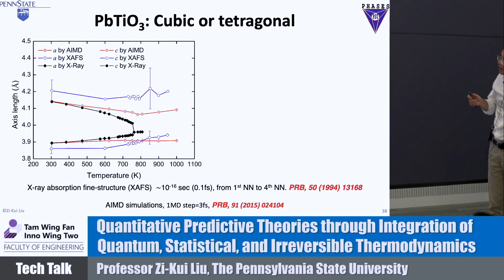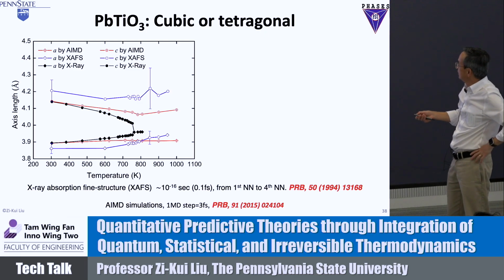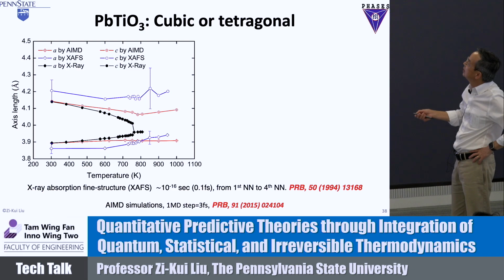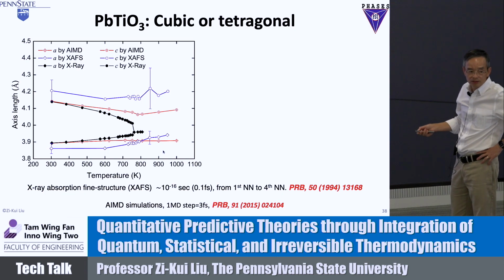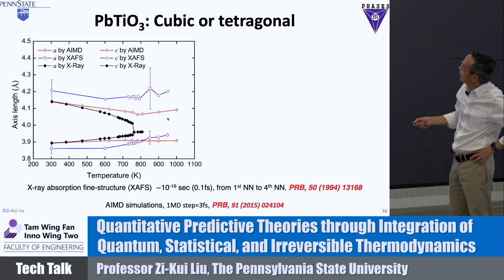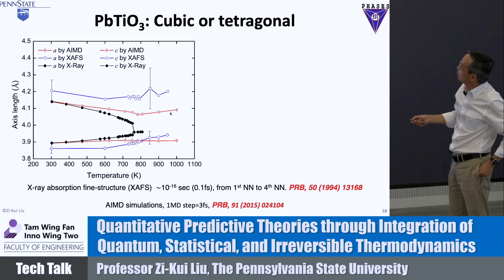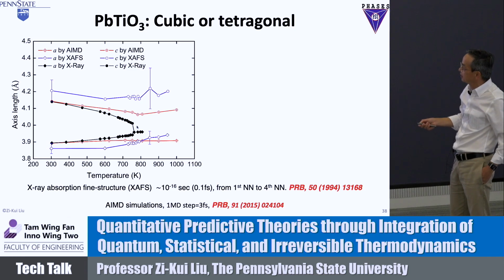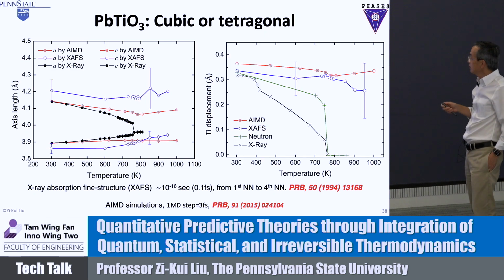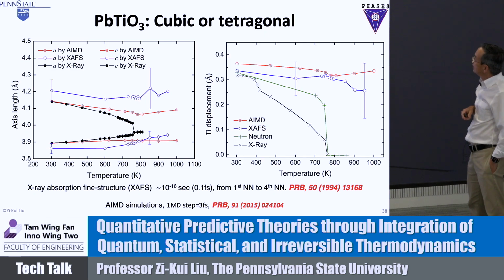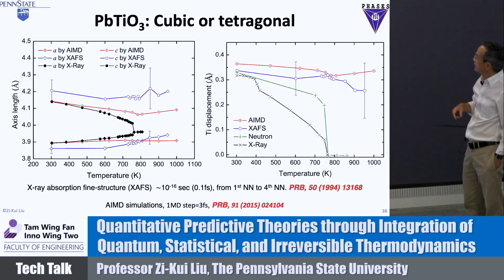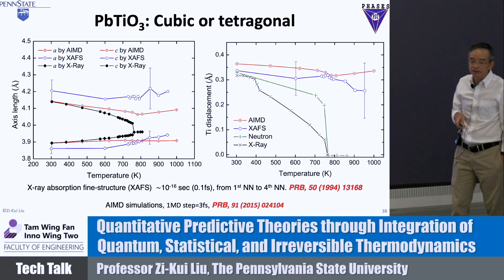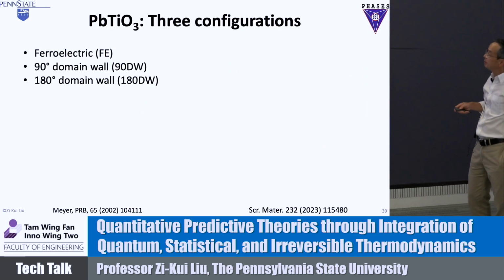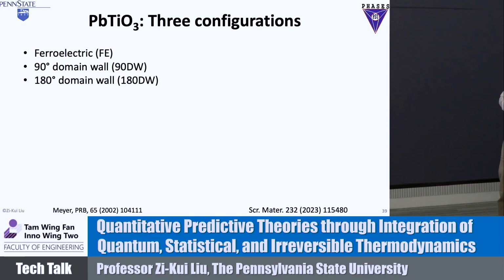It turned out the experiment was already done, in a paper from 1994. People did X-ray measurements. They showed that even above the cubic transition temperature, it's always tetragonal locally. This is our AIMD simulation, the red one in that picture I had, because we took the experimental lattice parameter and simulated it. You can see the polarization too. If you look at X-ray and neutron scattering, you get 0 polarization macroscopically, but locally you always have it. So we need both, but now the last problem: how can we predict it?